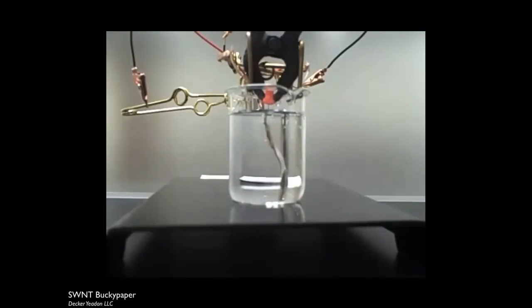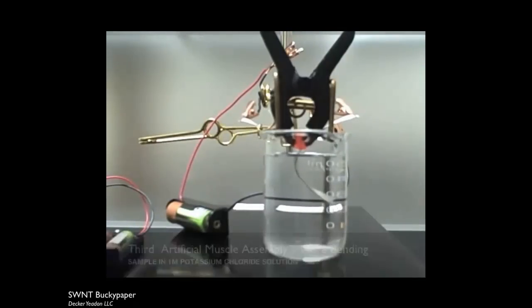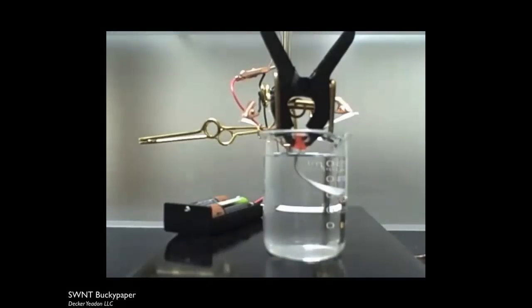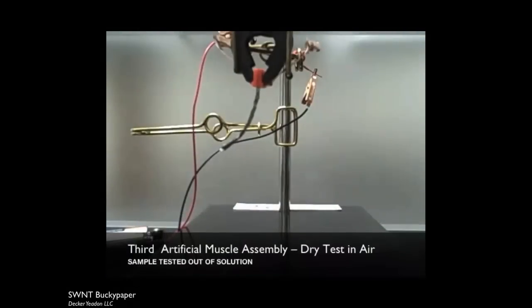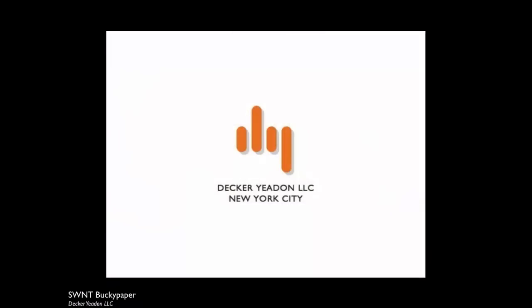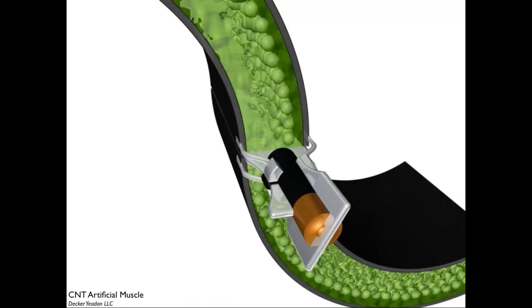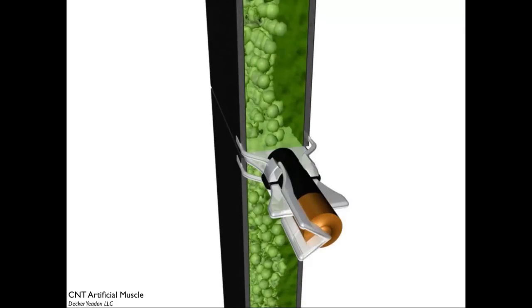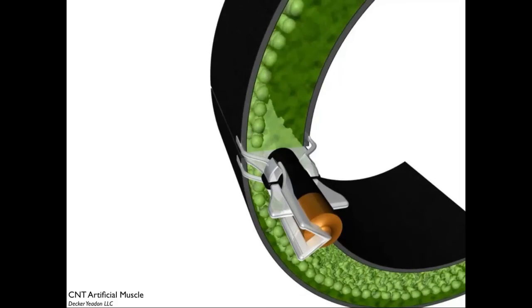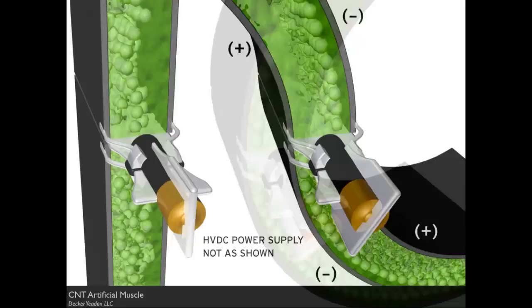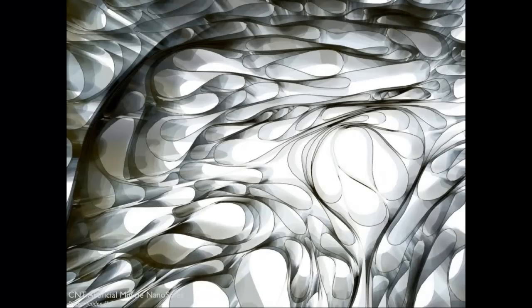We assembled or used these flexible electrodes for another type of muscle that we've used in our research. It's an ionic electroactive polymer, and depending on how you apply the electricity, how you switch the poles around, it will bend in one direction or another. This happens because the ions within the polymer will migrate to one side of the material sample or the other, and it will create swelling of the material on one side and shrinkage on the other, which means you have a bending actuator.